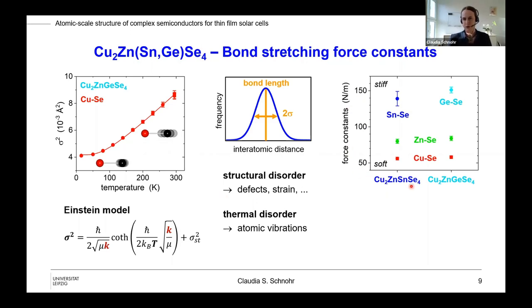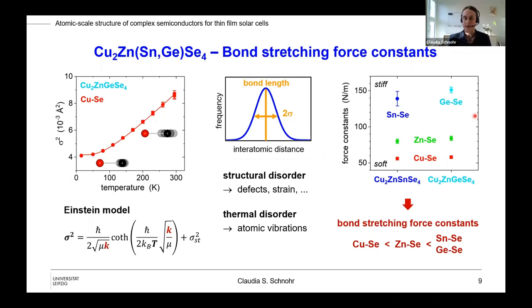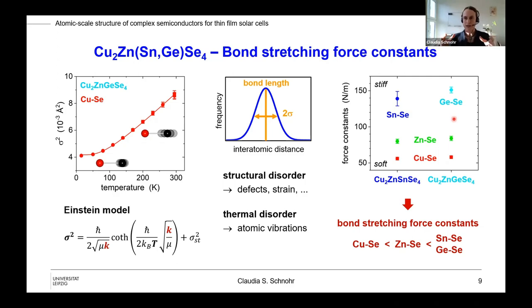We can extract the bond-stretching force constants for the tin compound and the germanium compound, for the copper-selenium bond, the zinc-selenium bond, and the tin and germanium-selenium bonds. Copper-selenium has the lowest force constant — it's the softest bond in the material. Then zinc. The highest force constants are observed for the tin and germanium bonds, which are the stiffest bonds. This correlates very nicely with the ionicity of the bond: the more ionic a bond, the softer it is; the more covalent the bond, the stiffer it is. So if the lattice changes due to alloying, we would expect the copper-selenium and zinc-selenium bonds to respond more than the tin or germanium bonds, because they are much stiffer.